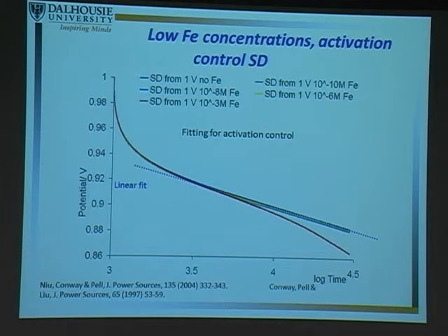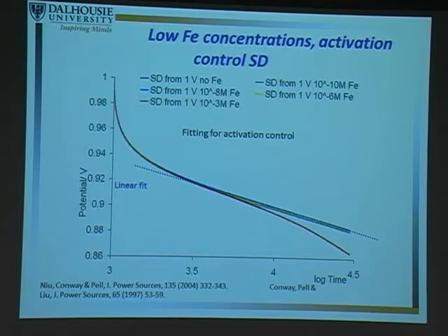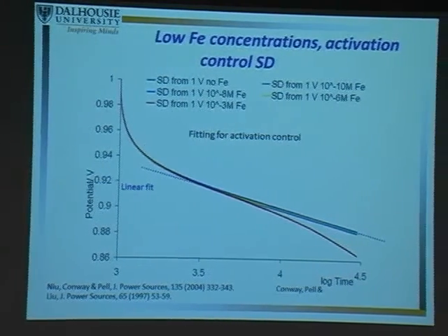But before we move on, we want to, again, use those models to try and figure out, can they give us guidance on whether this is a reasonable model. And so here we plotted this function as a function of log time. We see that linear drop. It's not surprising. We actually expect this for charge redistribution. Nothing here was surprising until we get to the 10 to the minus 3, where it starts to deviate away.